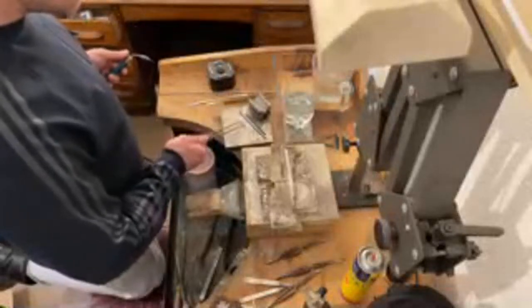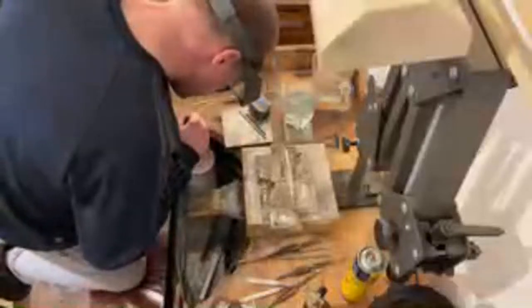Right, cool that off. Yeah, the thing with doing it this way, the gold builds up quite a lot of oxide. Doing it this way on the surface plate, the gold is definitely developing a lot more oxide in the cooling process than it would quenched, or than the silver is. I don't think the gold's liking this. The silver is, however. Yeah, the silver's cool. It's not zero oxide on it, as if you've pickled it. Pickling it bleaches it.